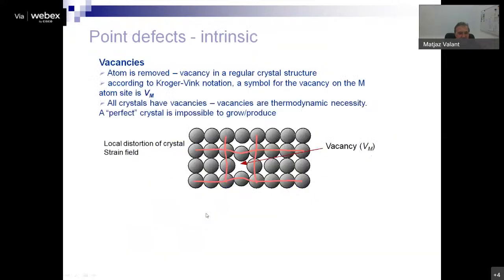So here we go now. First, point defects, intrinsic point defects. So I said vacancies. That simply means that one particular particle is missing in the lattice. So other particles accommodate to this defect, and of course they move a little bit towards the vacant site, which means that there's a strain generated within the lattice. So all these intrinsic point defects are also associated with a strain field in the lattice. There's a special notation we use to describe such defects. If there is a vacancy, the symbol for the vacancy on a particular atomic site is like that: V with a subscript M.